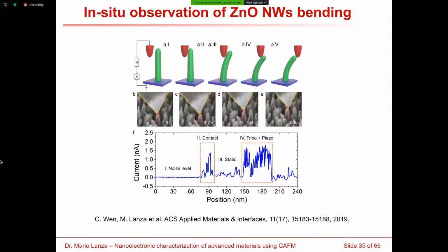Because we see one peak of current when the tip touches the nanowire, even if it's not bending it, and another peak of current when the tip starts to slide on the nanowire, even if it's not bending it. So if the nanowire is not being bent, the current cannot be related to piezoelectric effect. It should be related to these two phenomena that I have just described. So that's the beauty of this setup. We could demonstrate this because we were seeing the bending of the nanowire in situ during the scan. Thanks to the SEM, of course.